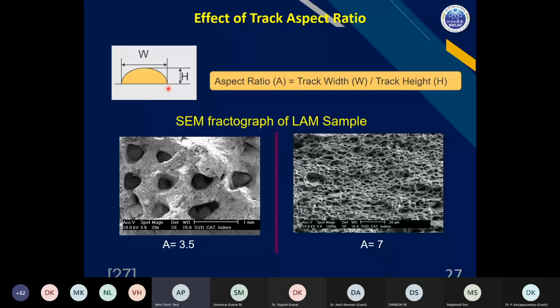See what is happening if the aspect ratio is more than 5. Somewhere here you get a very solid deposition, or if it is less than 5, maybe 3.5 or so, you will get porous caves. This is what is happening. And what I want to say is, when you have such reproducible inter-run porosities, you can think of depositing a porous structure.